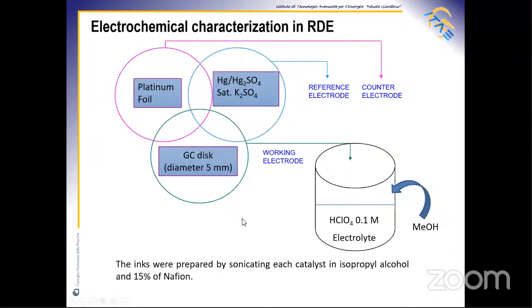After physicochemical analysis, we can discuss the electrochemical results. The rotating disk electrode measurements of the catalysts were performed at room temperature using a conventional three electrode cell. The working electrode was a glassy carbon disk of 5 millimeters where the thin film catalyst was deposited. The catalytic inks were prepared by sonicating each catalyst in isopropyl alcohol and 15% Nafion ionomer, and then added onto a GC disk to obtain a 50 microgram per square centimeter catalyst loading. The base electrolyte was a deaerated 0.1 molar perchloric acid solution in which methanol was gradually added to investigate the tolerance of the catalyst to the poisoning caused by this organic fuel at the cathode side.